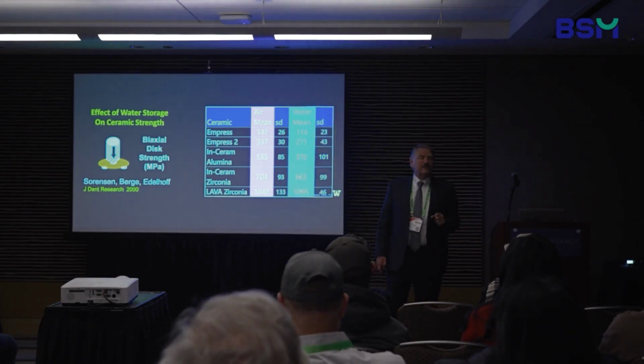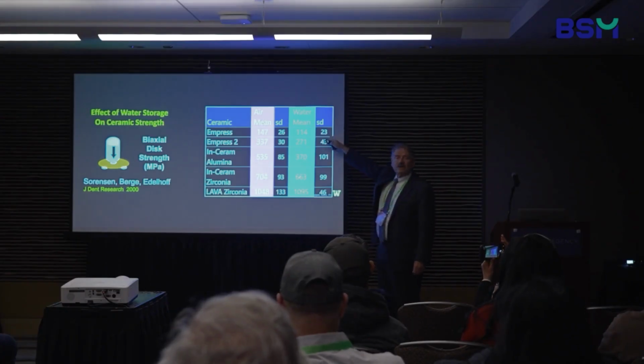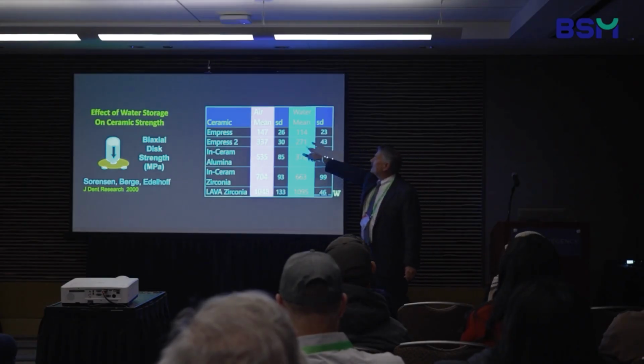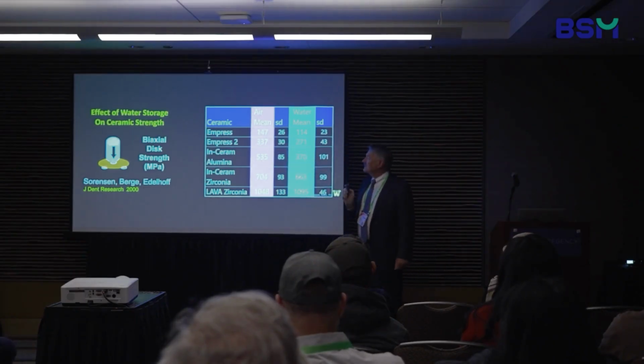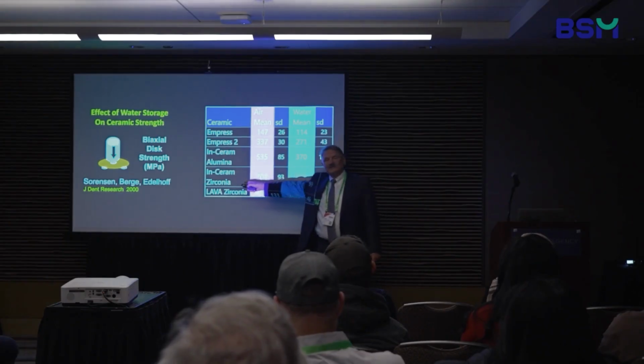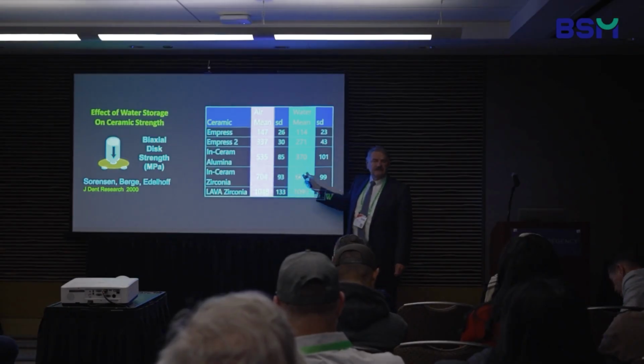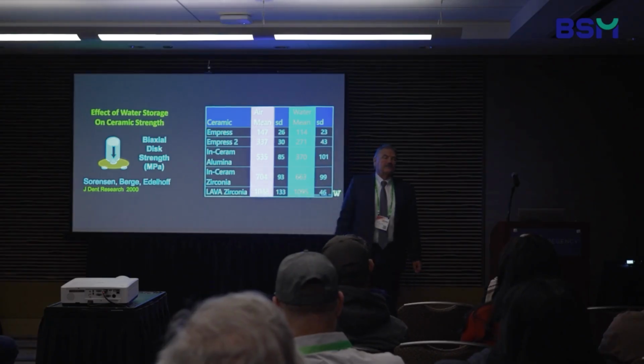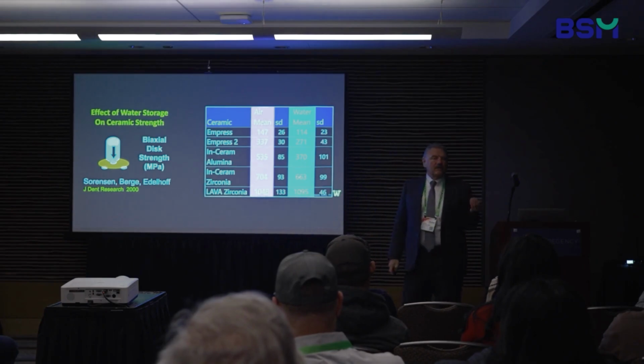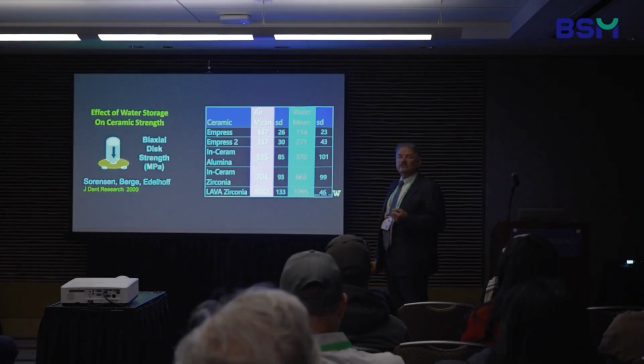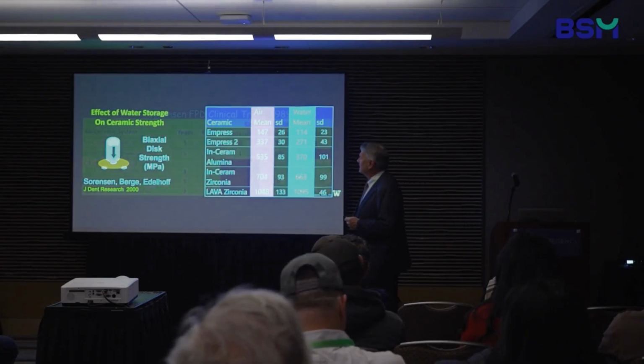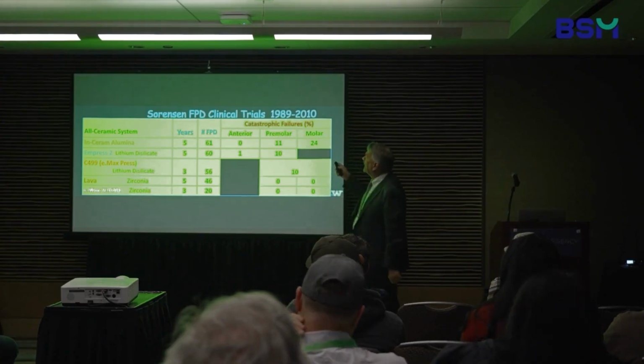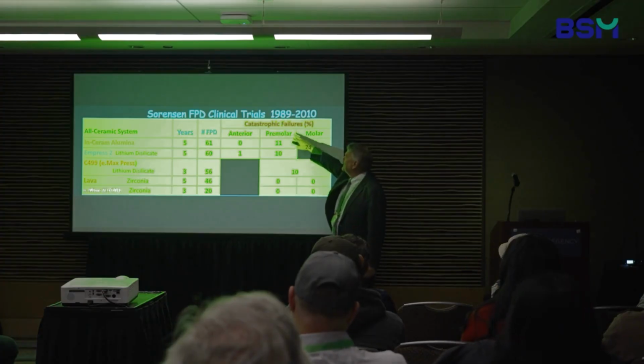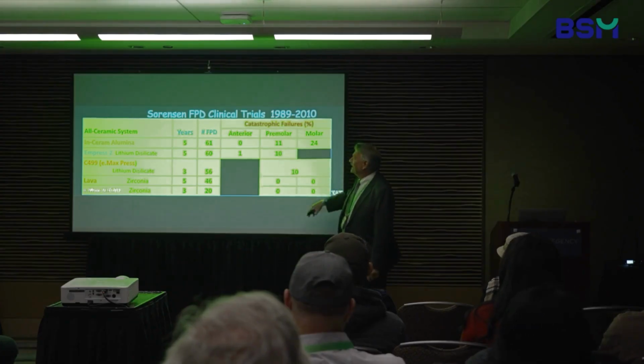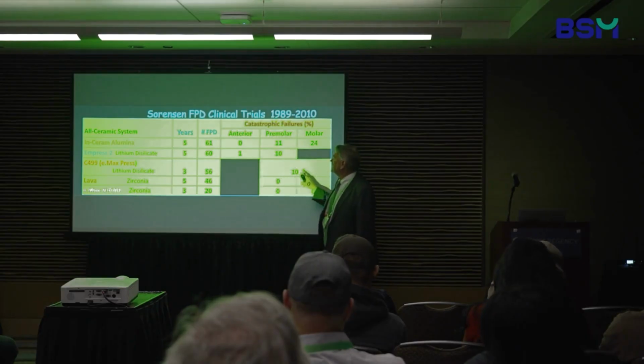But look how much the strength of these ceramics dropped in water over that 1 week, 7 day period, where we're seeing pretty significant drops in the strength of the materials. Even with the In-Ceram material, a big drop off. And then what do you know, for some of the zirconia, which was again not completely zirconia, we had no statistically significant change, and Lava zirconia was not affected by moisture. So now we're starting to go, all right, we have a serious material here that really will show some promise. And again, back then we were using it as a veneering material. So this is my experience in doing clinical trials on bridges in the premolar area, 11%, 10%. Then the Emax pressed material, about 10%.